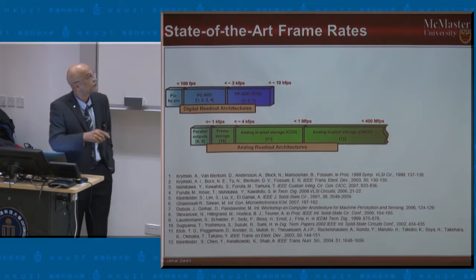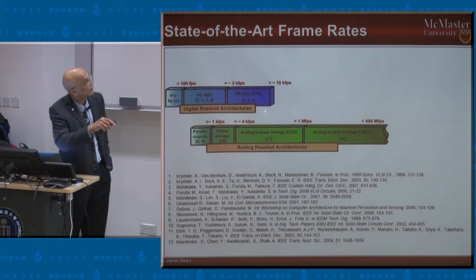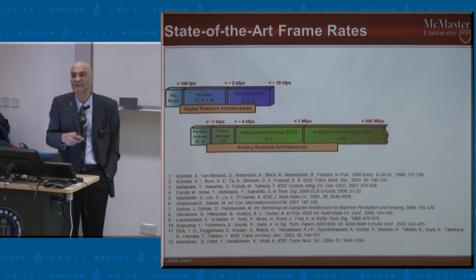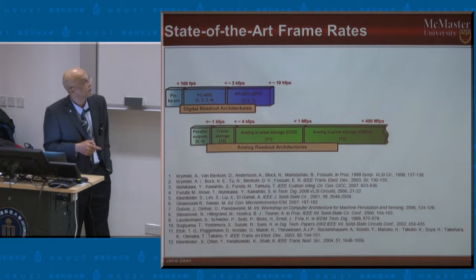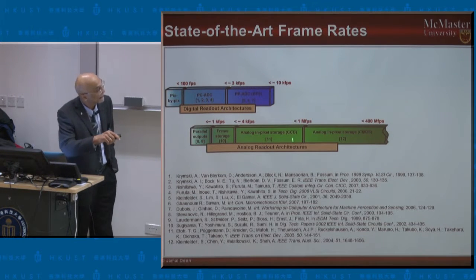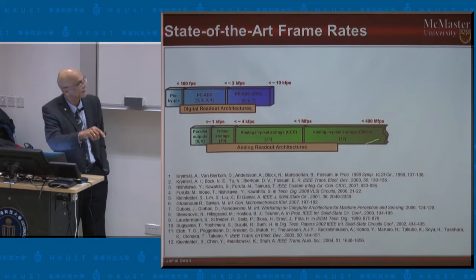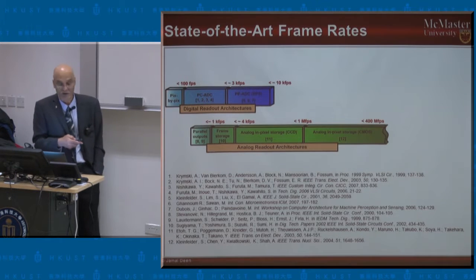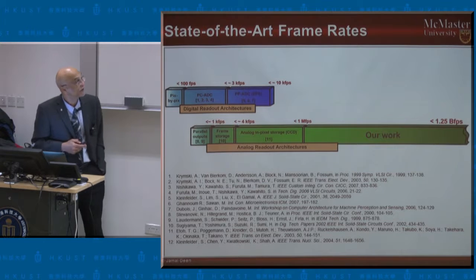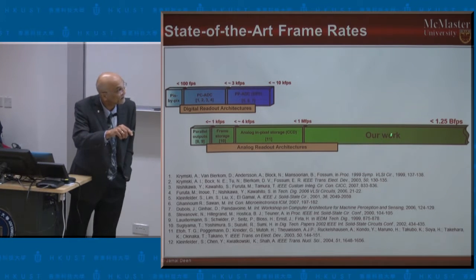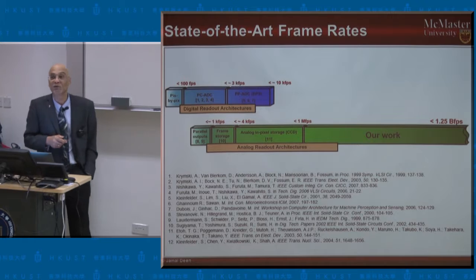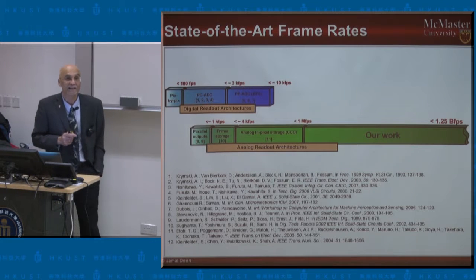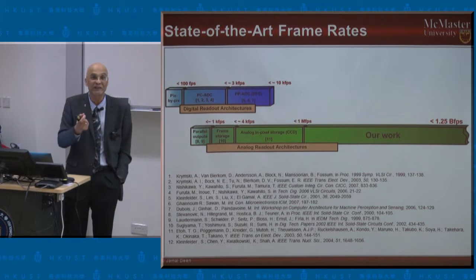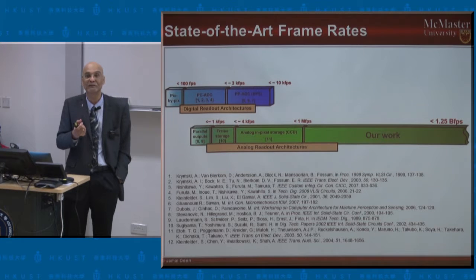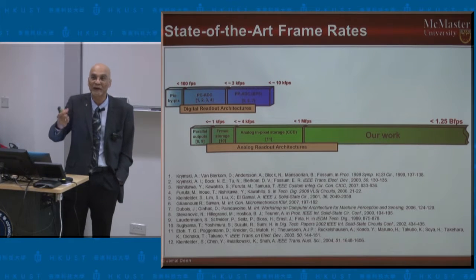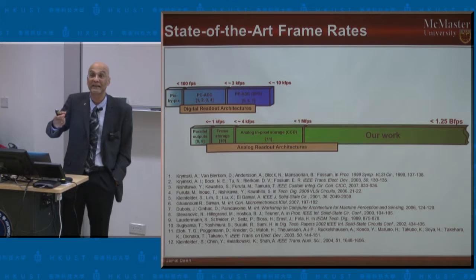If you look in the literature, if you have digital readout architectures, typically you're limited to several tens of megaframes per second. And if you have analog readout architectures, you're limited to a couple hundred megaframes per second. Using this new procedure, we are able to push the speed to 1.25 billion frames per second. This means that you can capture an image with a sub-nanosecond response time. And I'll explain to you why we want to do such high-rate image capture.